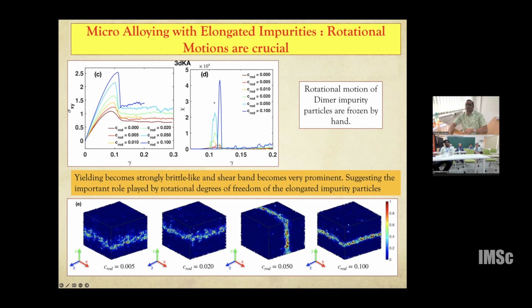which tells us that the rotational degrees of freedom of these dimers are extremely important for promoting or stopping this shear band formation. So when they cannot rotate, they somehow concentrate or localize all the strain to form shear bands. Which you can see in this snapshot. When you have some amount of dimers, then you have some shear band, but the shear band is somewhat diffuse, in the sense that the width is significantly large. But if you increase the dimer concentration to at least 5% or 10%, then the shear band becomes extremely narrow. And that is also signaled by a very sharp stress drop in panel C, which was supposed to be A, but I have taken it from the paper itself, and it's a cut and paste problem. Sorry for this.